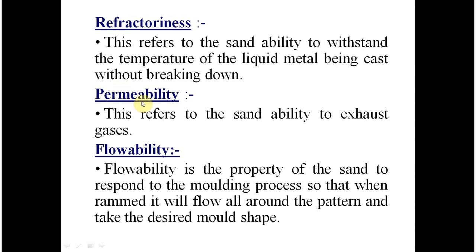Permeability refers to the sand's ability to exhaust gases. When we pour the molten metal, many gases are produced such as hydrogen, nitrogen, carbon dioxide, and steam, which should leave the mold. Otherwise, casting defects will occur such as blow holes and gas holes. So the permeability property is very important.